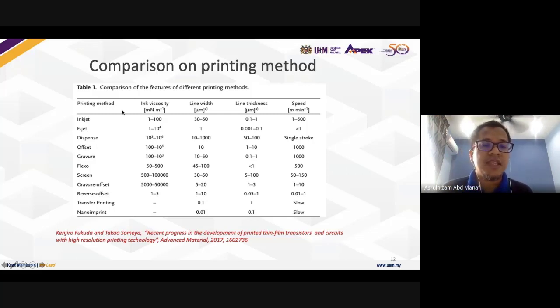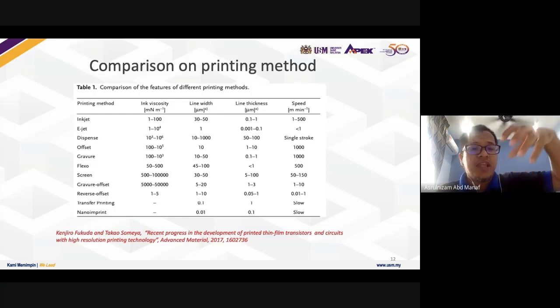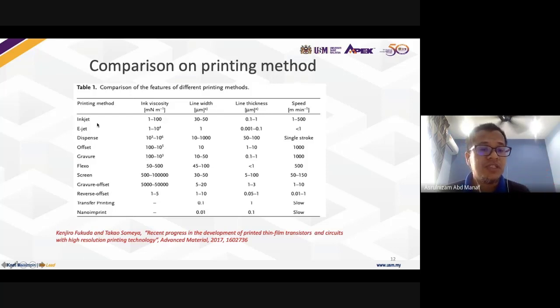So you have to match the type of your printer with the properties of your ink. That's why if you purchase the ink from overseas, you have to ensure the properties are matched with your type of inkjet. So this is a few viscosity considerations. Basically, for inkjet it cannot be a paste, otherwise the nozzle cannot operate properly. If you use screen printing, the ink must be in a paste condition,